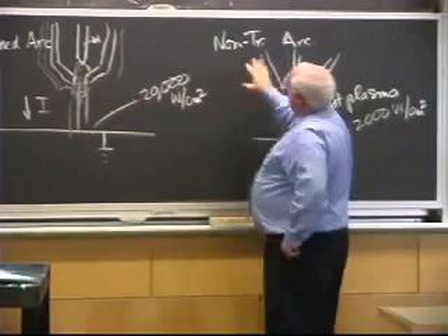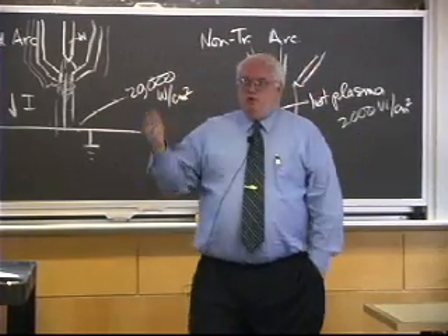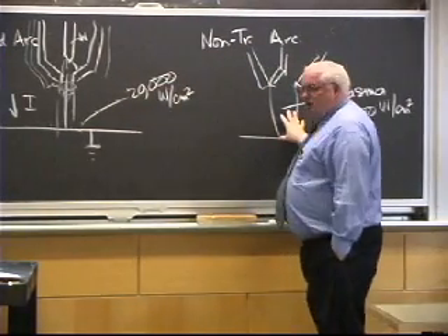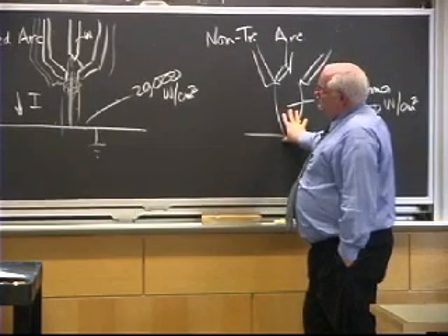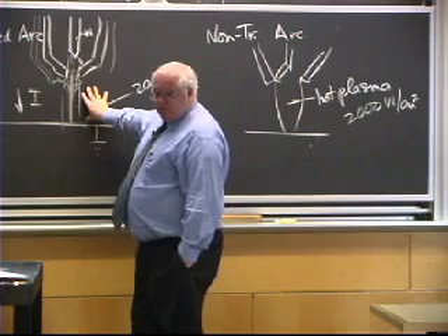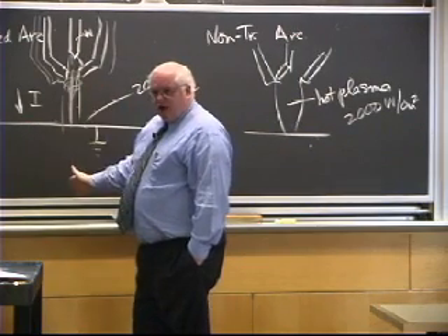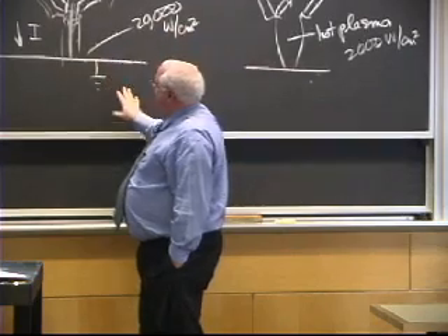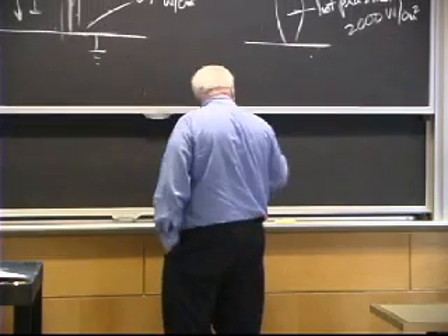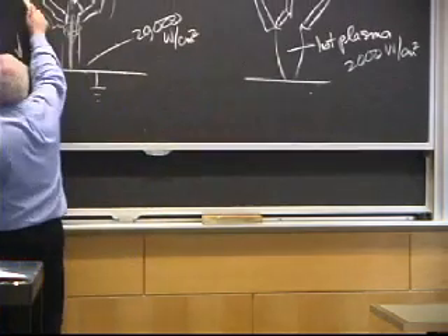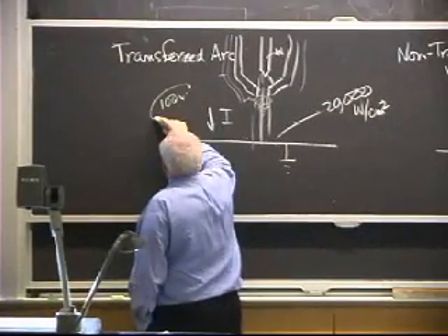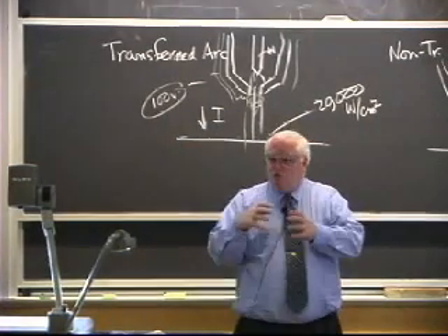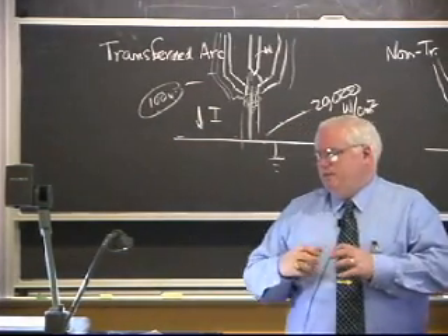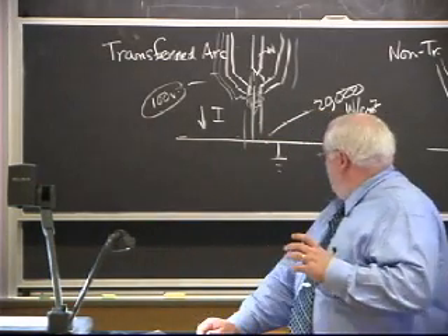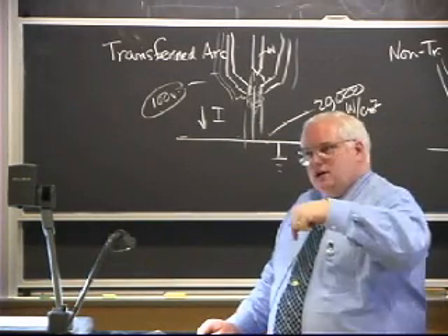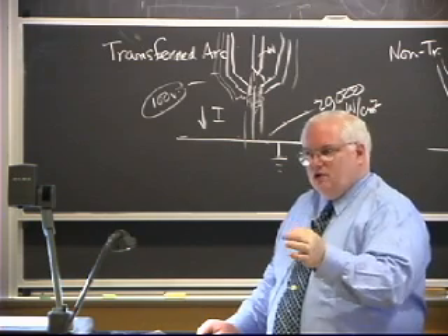So there's a big difference, and again, the difference between transferred arc and non-transferred arc, both of which are used. This one is used primarily when we don't want very much heat, or we're trying to heat something that's non-electrically conductive. This is always used for cutting. You need that type of heat intensity to do the rapid melting that you need for cutting. So you're always going to have a transferred arc for cutting. And in fact, because it's a constricted arc, you may have in here not just 30 volts, but you can have 100 volts across this thing because you've quenched that arc on the outside, made it narrower, sharper, concentrated the heat, and that's going to require a higher voltage to get the higher temperatures in the plasma to cause greater ionization in the smaller cross-section.